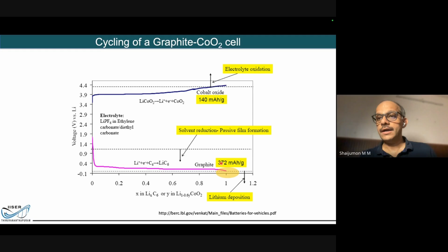Right? So these two processes are happening simultaneously, and there is a voltage at which this lithium cobalt oxide oxidation reaction happens, and there is a voltage at which the intercalation of lithium between these layers happens, and that is very clearly marked here, around 0.2, 0.3 volt here, and around 3.9 to 4.1 volt here versus lithium.